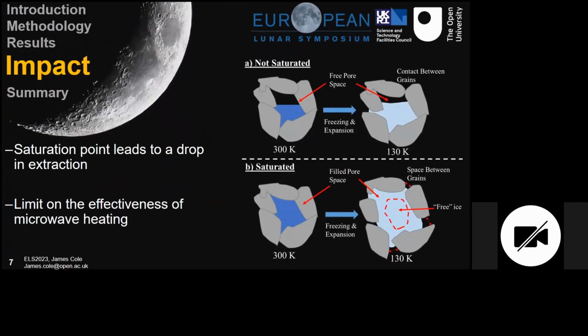So our theory about what's happened here is that before the saturation point, when you're filling the pore space with liquid water before you freeze it, there's still space. So when the water expands as it freezes, the grains stay in contact. And the important thing to remember here is that the simulant grains are what's heating up, because they interact with the microwaves more strongly. By having this contact, you get more efficient heat transfer, and therefore your water extraction continues. At the saturation point, however, the pore space is filled.